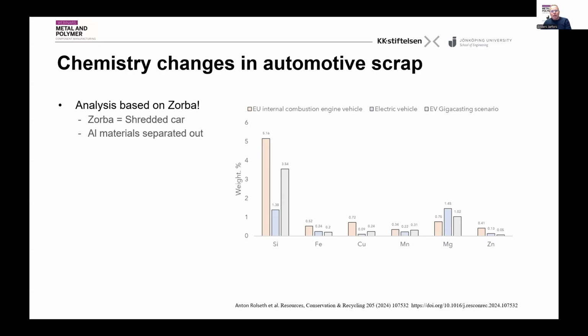So in this study, they had also been shredding electric vehicles. What you see when you shred the electric vehicles is that you do not get 5% silicon anymore, you get 1.3% silicon. So that means downcycling here means that the scrap would increase its carbon footprint, and increase the amount of energy that would need to be put into the recycling process if you want to increase the silicon content. Now, the problem is also that the combustion engine is disappearing. So that means that zinc will no longer be there. So one needs to rethink the material flow completely.